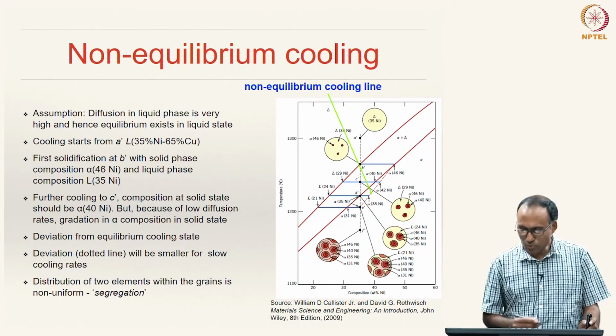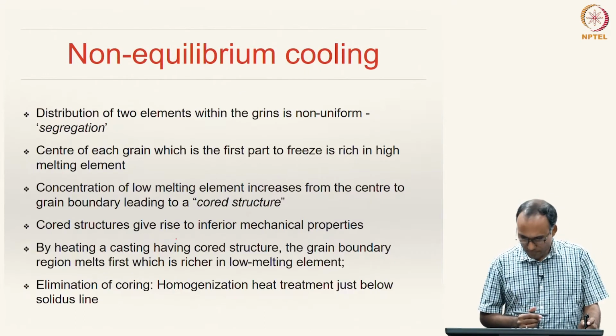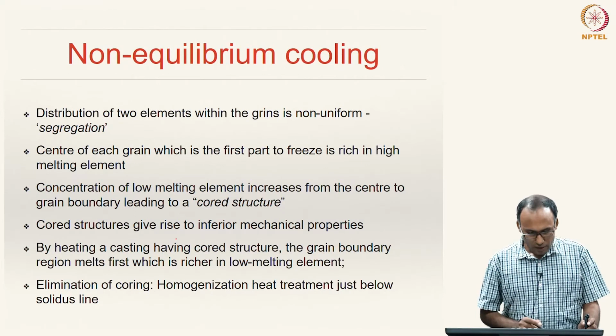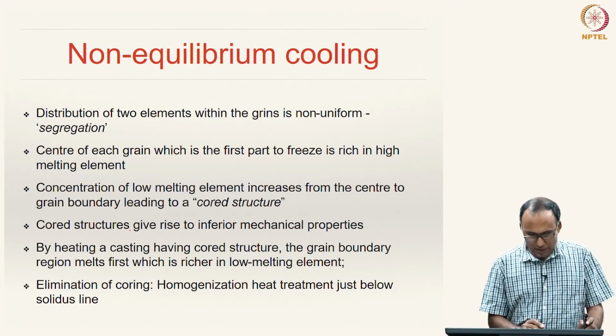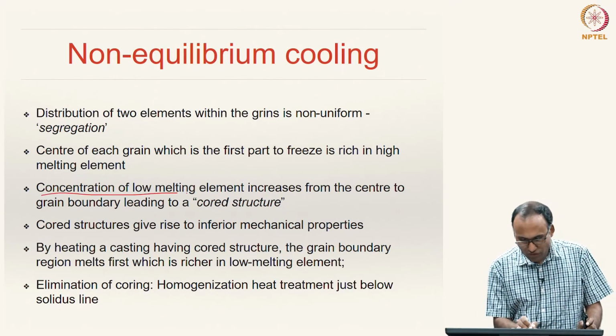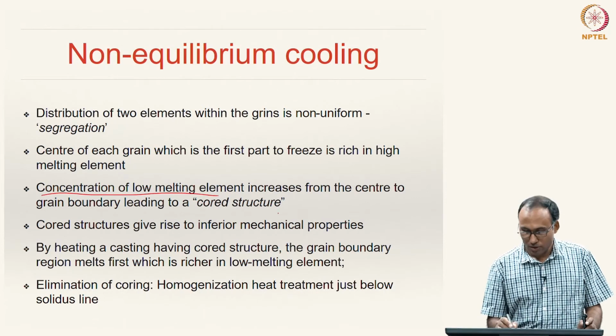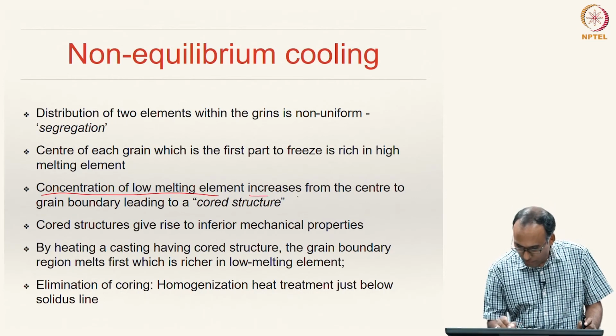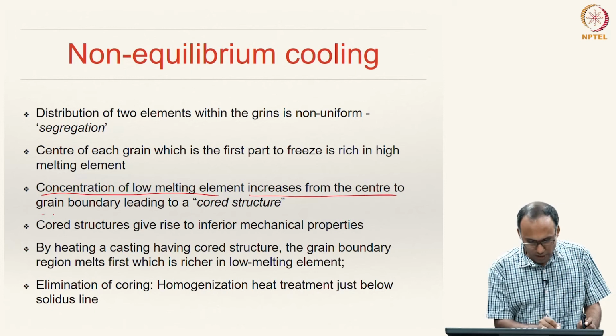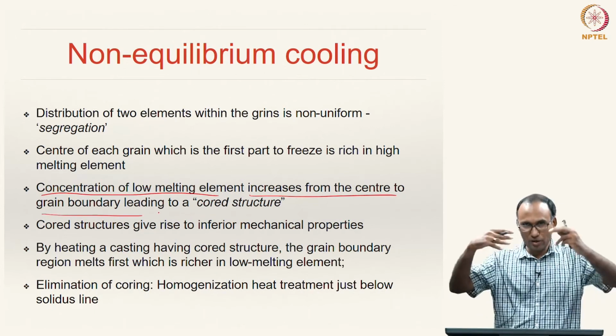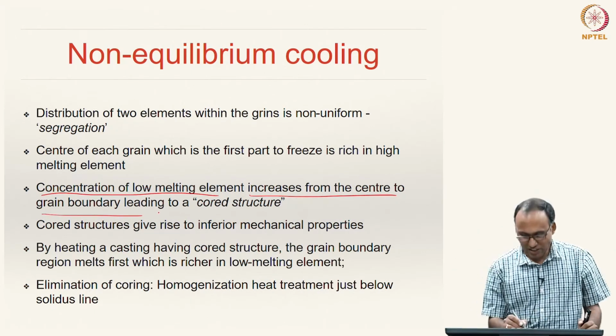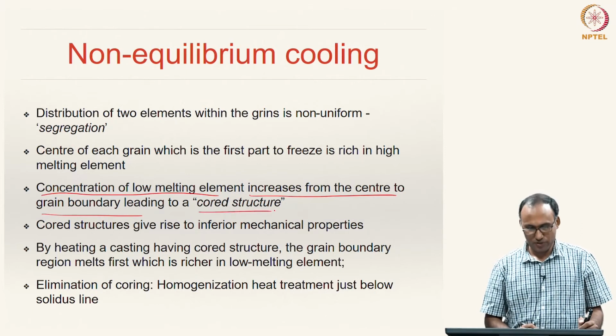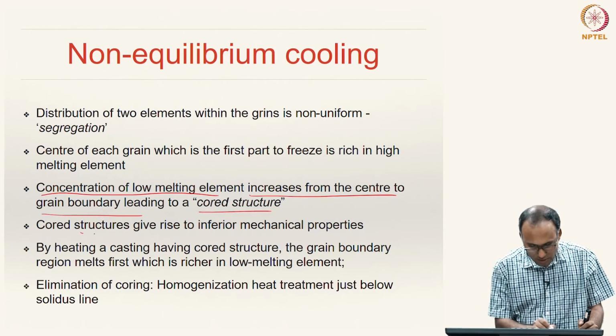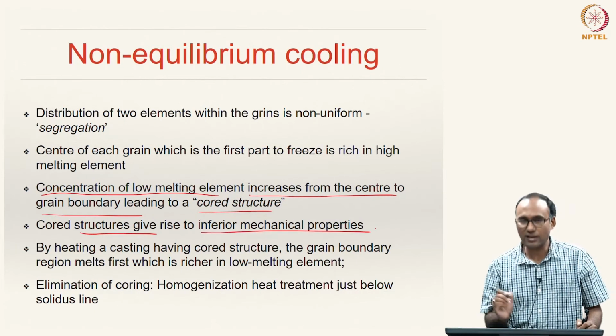So, this process is called segregation, and so the core structure, the problem with the, so that means that you have a higher concentration of low melting element increasing from the center of the particle to the grain boundary, that means the boundary where two grains meet, and such a structure is called cored structure, and this cored structure gives rise to inferior mechanical properties.